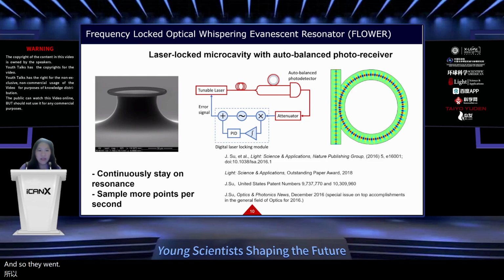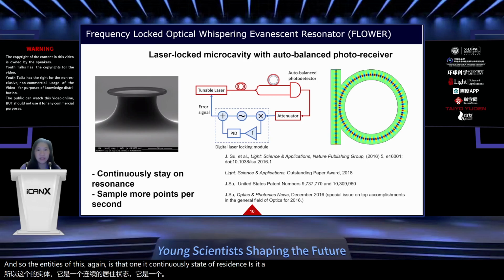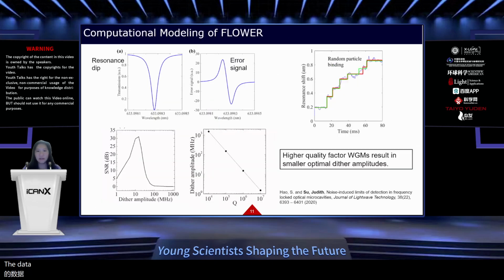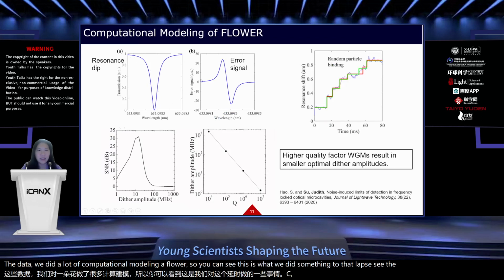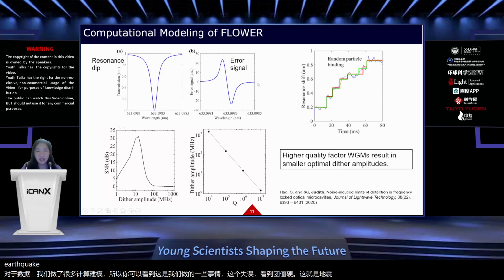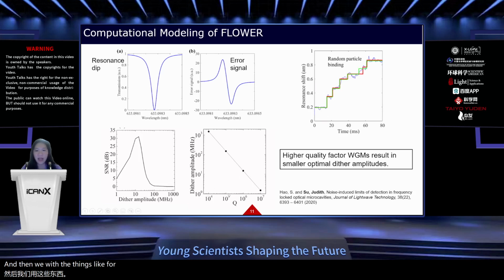The advantages of this, again, are that it continuously stays on resonance instead of slowly scanning past resonance, and you can also sample more points per second, which permits more averaging of your data. We did a lot of computational modeling of FLOWER, in Simulink and MATLAB. You can see your resonance dip, and this is what the error signal looks like. We looked at, for example, as the quality factor, which is related to the photon lifetime of your cavity, increases, what the optimal dither amplitude is to multiply your signal with to get the best signal to noise ratio. This graph on the right is simulated data. You can see we have this random particle binding, and what can we pick out?